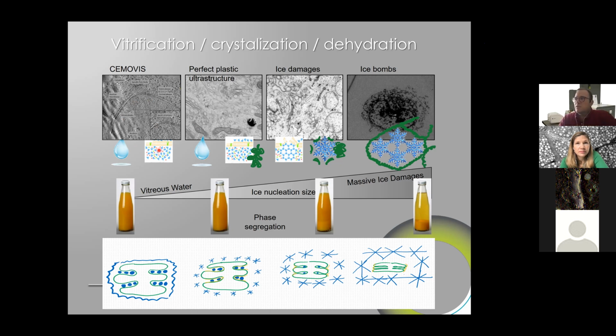When the water starts to crystallize, one of the big questions is that the ice crystals start to grow and push away the material which is inside. The second point is that the crystal tends to like being as pure as possible, so it will extract the water from the molecules surrounding it so that it can grow. Doing that, it progressively dehydrates the proteins around it, which gives us this kind of gradient